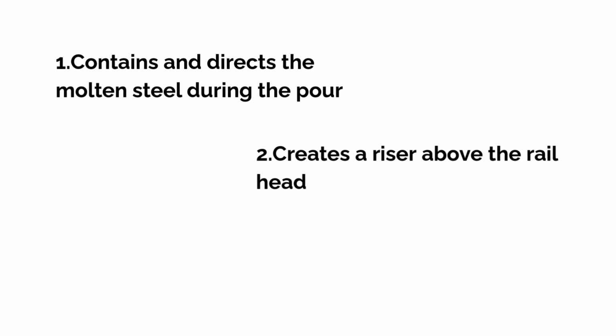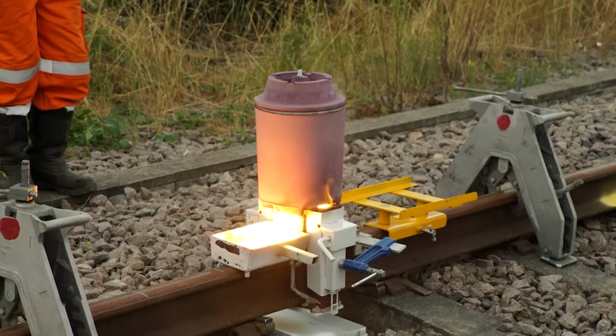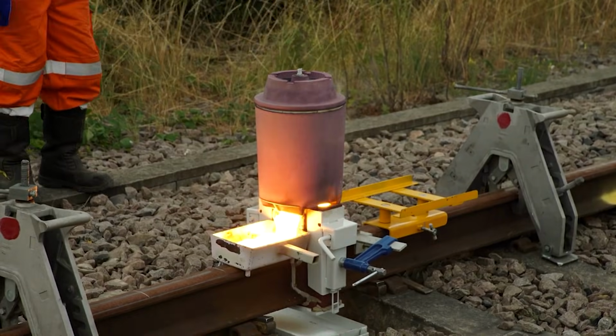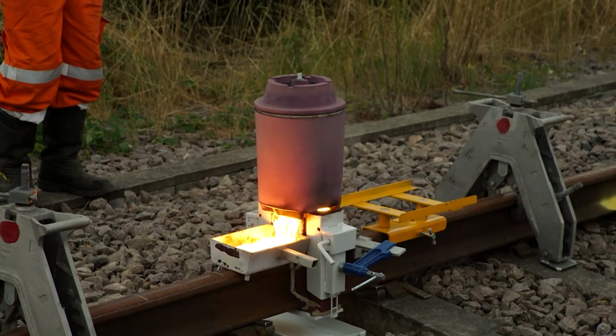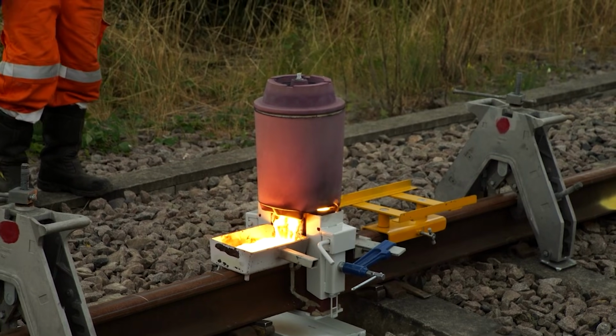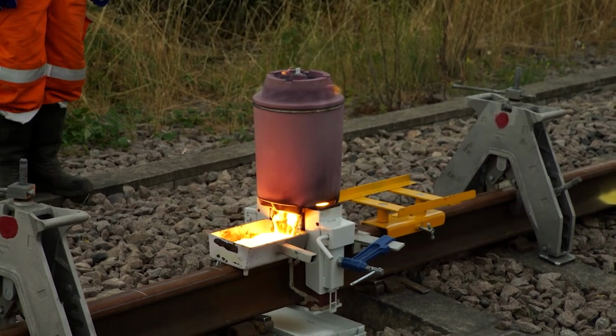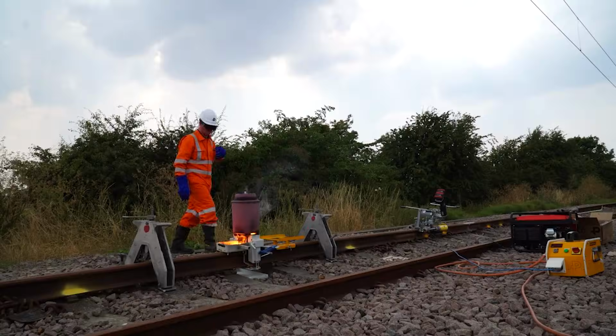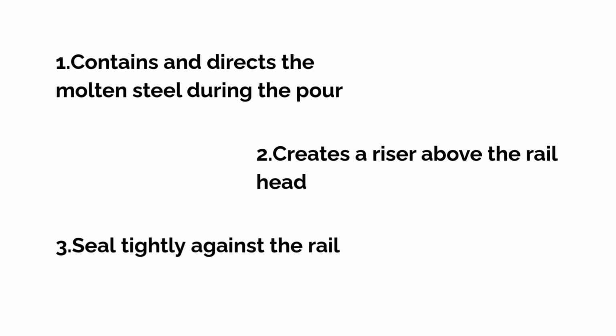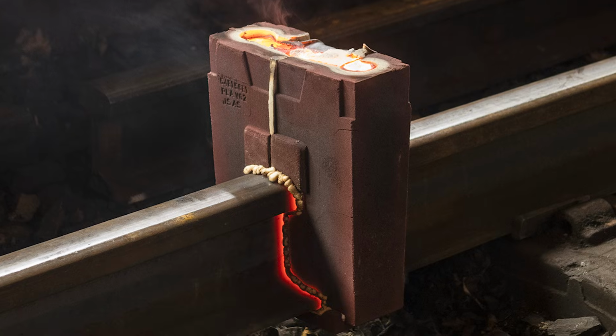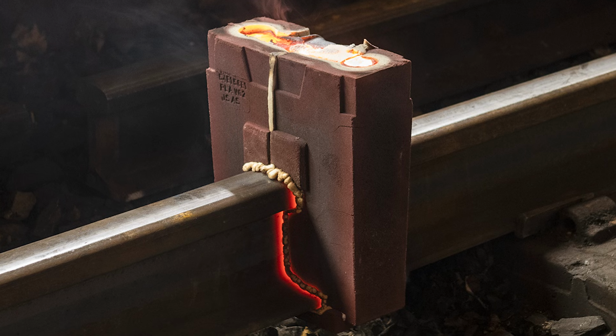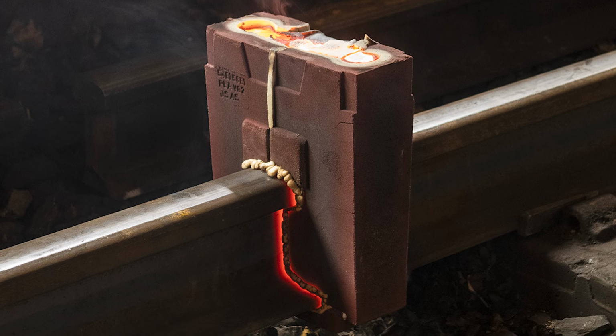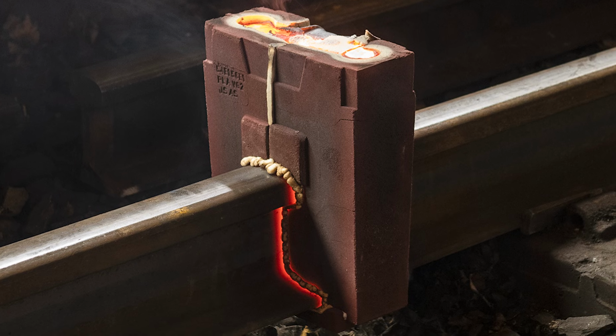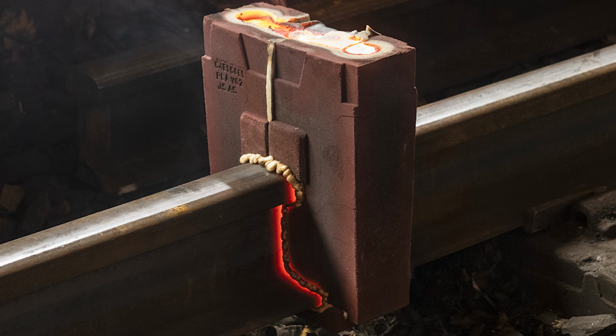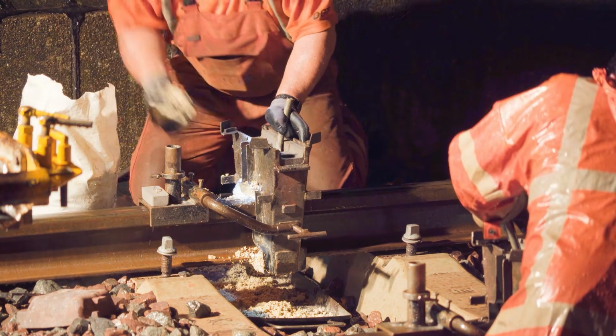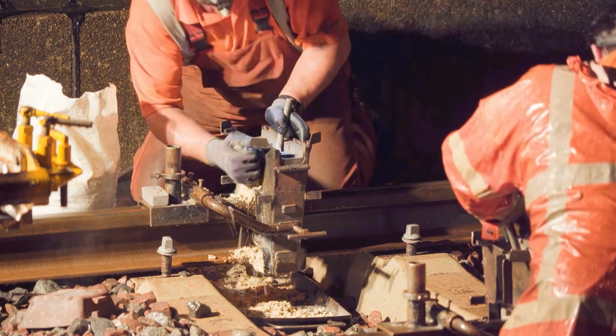Second, it creates a riser above the rail head. This acts as a reservoir, feeding more molten metal into the joint as it cools and shrinks, preventing voids and internal defects from forming in the load-bearing area. And third, it seals tightly around the rail. Any gaps would allow molten metal to run out or air to enter the mould, which can weaken the weld, distort its final shape, or starve the joint as the steel solidifies. Get the mould wrong, and even a perfect alignment and chemistry can't save the joint.